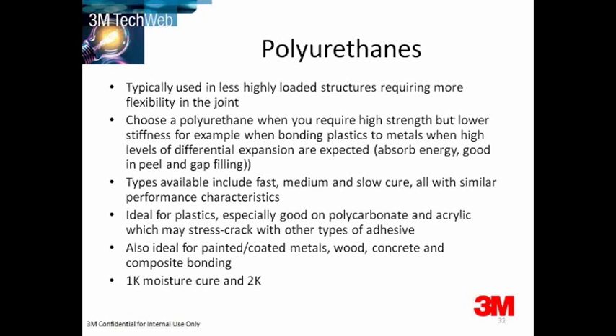Polyurethanes — we showed an example earlier with the DP620 and its lovely energy-absorbing characteristics. They are typically used in less highly loaded structures, but you can get up to 30 MPa strength from a PU where you need more flexibility. Where you need high strength but lower stiffness — for bonding to plastics, or in impact scenarios where you need to absorb energy — PUs are ideal. Available as one-part moisture cure or two-part chemical cure.